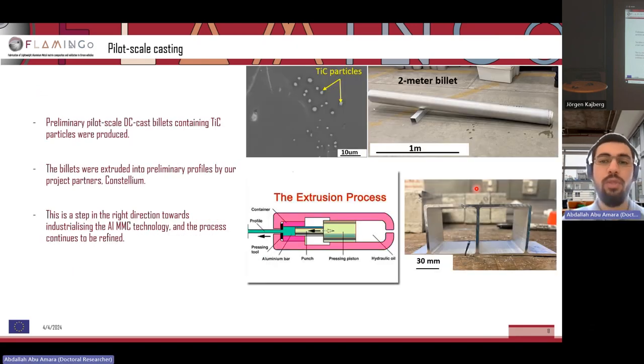So we were able to produce some pilot scale preliminary DC cast billets. You can see this is a 2 meter long direct chill cast billet, and we had added titanium carbide particles, and we were able to identify these titanium carbide particles in the microstructure. So we had successfully incorporated them in the DC cast billet. And then these billets were extruded by our partners, Constellium. They were put through the extrusion die, and we had some preliminary extruded material, which we're still optimizing the process and working on. But we have some preliminary extruded material that contains titanium carbide particles, and some pilot scale direct chill cast billets as well.